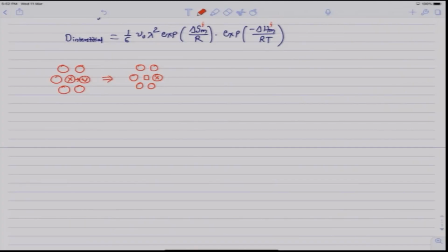Why is it not unity? Because the vacancy itself is making random jumps, and for the vacancy there is no barrier for vacancy formation as for the diffusion of X. The only barrier for diffusion is the migration barrier, and so the number of successful jumps of a vacancy per unit time will be much higher than that for the atom X. So, the vacancy itself will make n number of jumps, and after making n number of jumps, it can come back to one of the nearest neighbor sites of X, and then this X will make its second jump into that same vacancy.